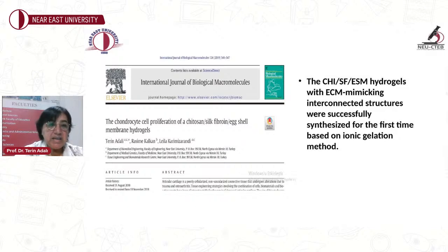So, in order to improve the mechanical property of the biopolymer in this design, we tried to find a material that can biomimic the extracellular matrix of the articular cartilage, and also has high biocompatibility and improves the mechanical strength of the hydrogel. So this is the first step of designing the bioink. Therefore, in this study, we used biopolymers such as chitosan, silk fibroin, and eggshell membrane to mimic the extracellular matrix.